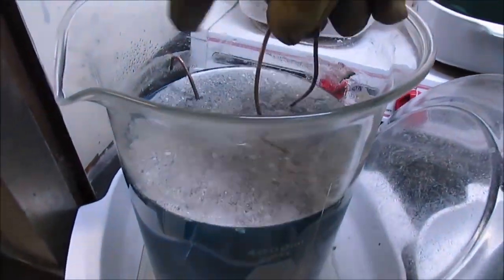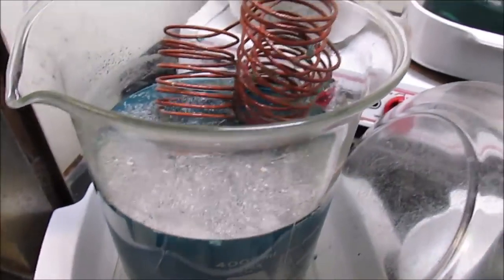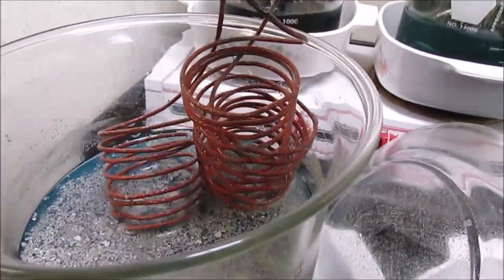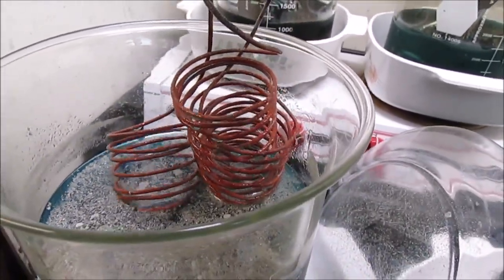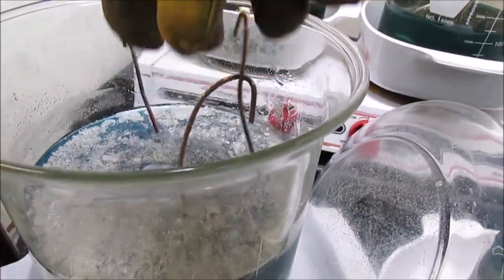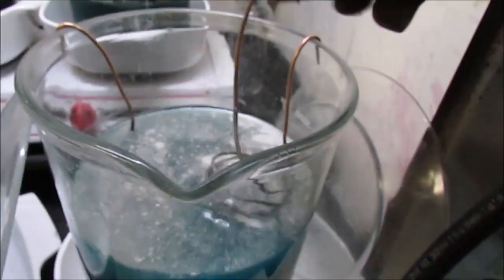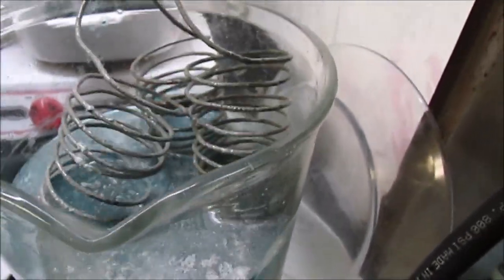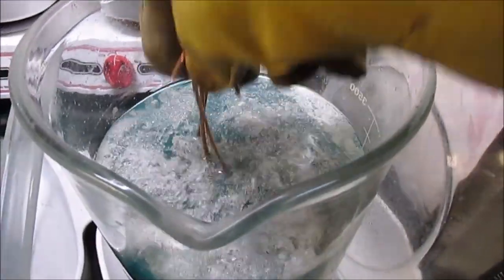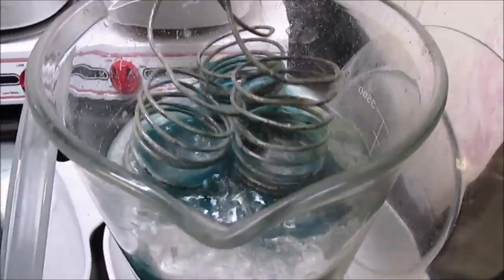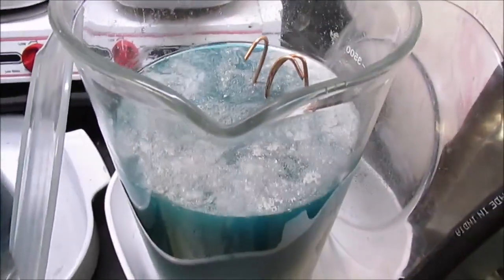One of the questions in the comment section from part 1 was, how can I tell when the silver's cemented out? You see that pink colored metal there? That means the silver has come out of solution in that beaker. Over here, if you look at this, you'll see that there's still silver forming on the copper. That's that gray powder on the copper there. That means this solution still has silver in it, and that's how I tell the difference.